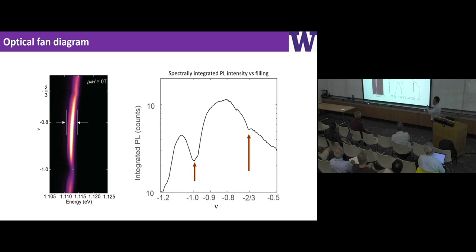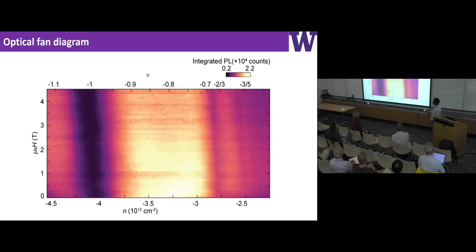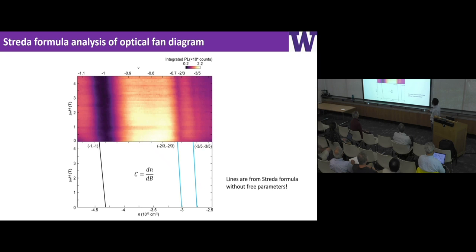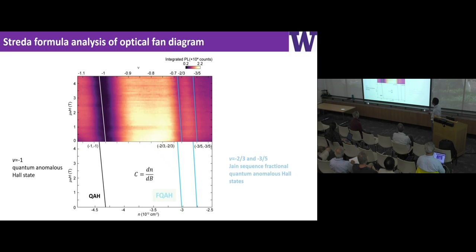Then I plot these line traces as a function of magnetic field and get these Wannier diagrams. In this Wannier diagram, you will see there are three features here, 1, 2, 3. Then we can compare these three features with the dispersion from the Streda formula analysis. These are the three expected lines from these topological states. And you can see all these lines actually fit my data really well. So from this comparison, what I conclude is that the state at filling factor -1 is a quantum anomalous Hall state, and the other two, at -2/3 and -3/5, correspond to fractional quantum anomalous Hall states.